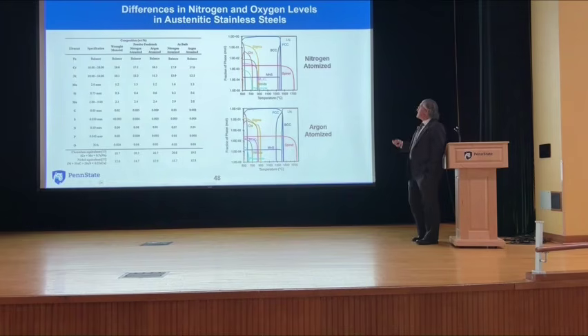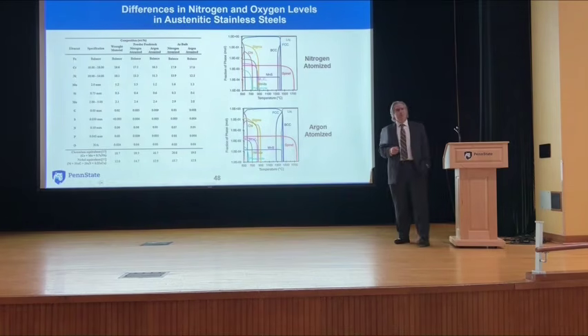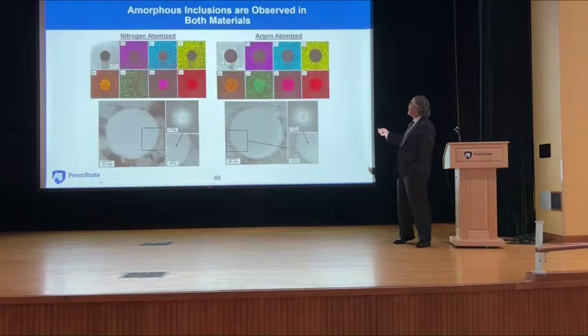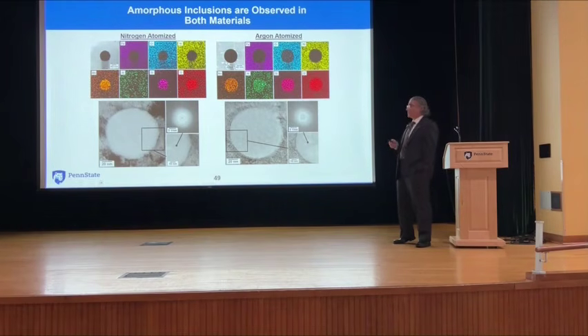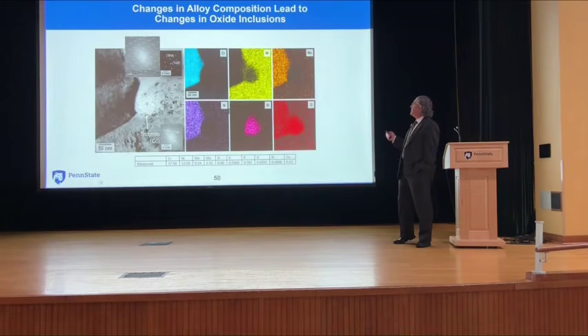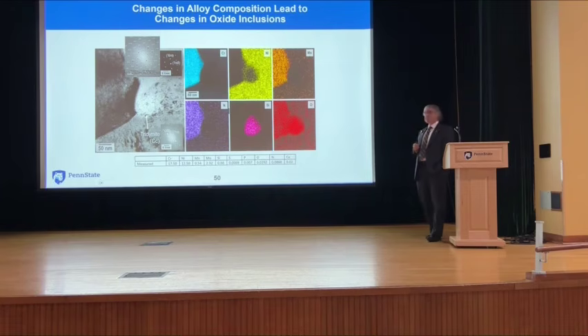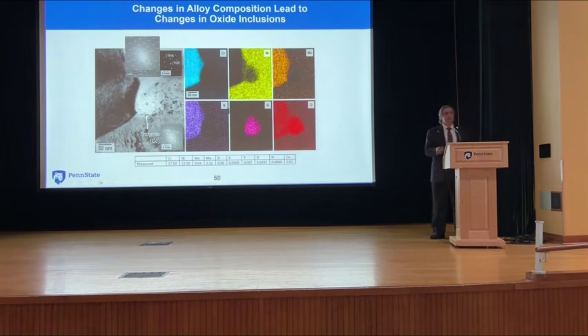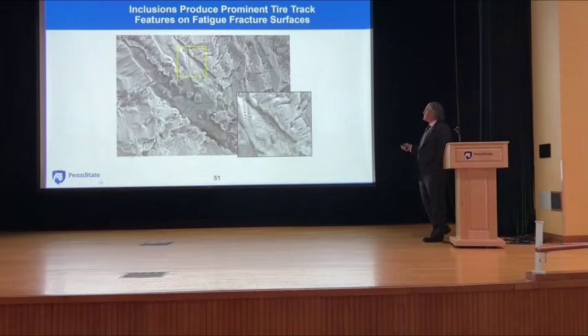And so even in austenitic stainless steels, you say, well, it's a problem in duplex stainless steels. Well, they show up in austenitic stainless steels too, whether I have a certain amount of nitrogen, low level, high level of nitrogen or not. Show up in basically 17-4s. They're there as well. And what you notice here is different names here. All the oxides are different. And so the complexity of these starts to go.